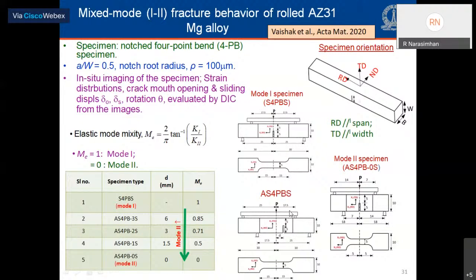In the asymmetric mixed mode specimen on the bottom right side, these are placed asymmetrically, and also the crack plane deviates from the midplane of the specimen by a certain amount D. By reducing that D, we can induce more shear loading at the tip. The mode 2 component increases as D decreases, as you can see from the table on the left side.